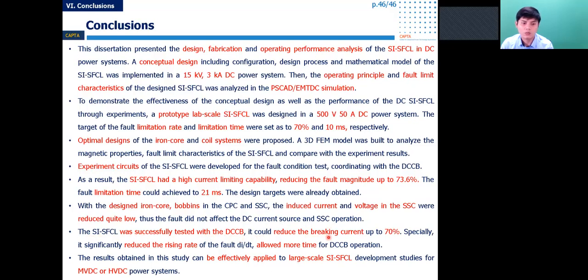It could reduce the breaking current up to 70%, and especially it significantly reduced the rising rate of the fault current, di/dt, and allowed more time for the DC circuit breaker operation. The results obtained in this study can be effectively applied to large-scale SI SFCL development for the MVDC or the HVDC power system.